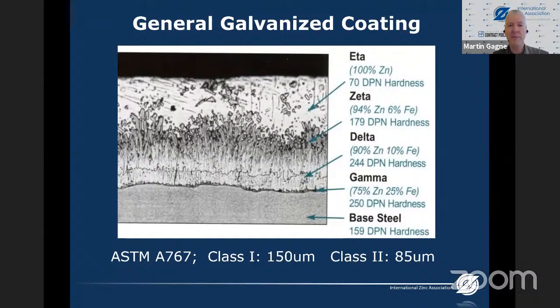same corrosion protection. In North America, the production of galvanized reinforcing steel is covered by a standard specification, ASTM A767. It has two classes, mostly dependent on the diameter of the rebar. For thick rebar, a class 1 coating is required, a minimum of 150 microns thickness of zinc. And for thinner bars, a class 2, a minimum of 85 microns of zinc.